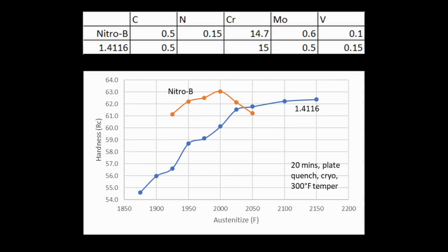Okay, so we got sidetracked a little bit, but yeah, so the Nitro-B, it gets more hardness. You can see in these curves that the 4116, it tops out in hardness, and no matter how much hotter you heat the steel, it won't get any harder. Because we dissolved all the carbide, all 0.5% carbon is in solution, and it's just not going to get to any higher level of hardness.